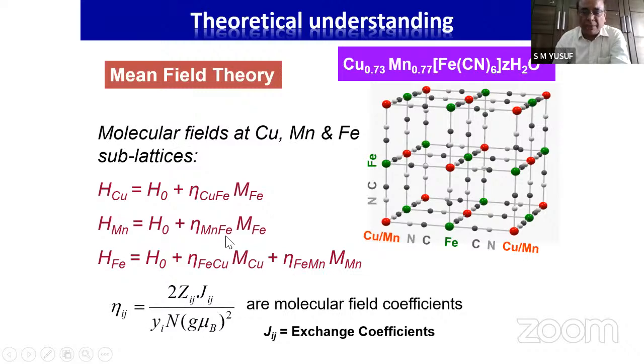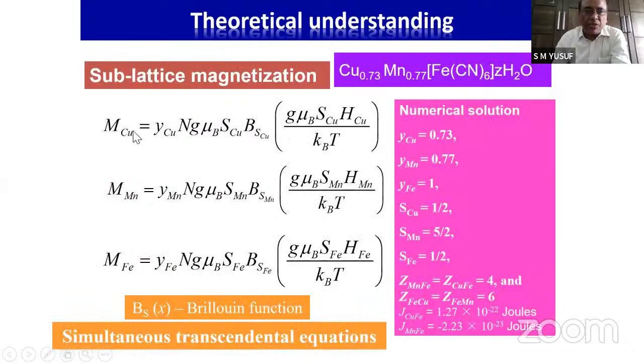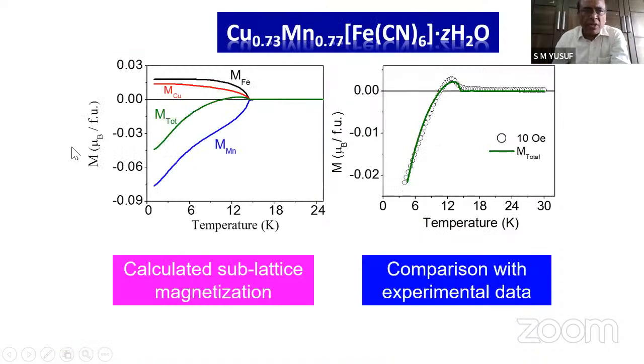And this is the molecular field coefficient, and we could calculate the sublattice magnetization using the Brillouin function, with all the numerical values relevant for our system. The J values are determined from the magnetization study. By doing this, we could calculate the magnetization as a function of temperature for the individual sites, iron, copper, and manganese, and the net one, the green one, is the net moment per formula unit. This is the mean field calculation. When I superimpose it on the experimental data, you see very nice matching, in the sense that it is able to reproduce this. So we could achieve a mean field understanding of this phenomenon.